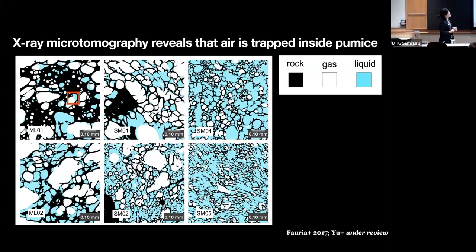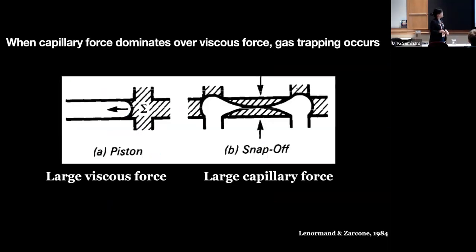Someone did some measurement using a technique called X-ray microtomography. They imaged the distribution of gas, rock and liquid when they did these infiltration experiments. And what they found is there are tons of air bubbles inside the ones that stay floated, okay? And why is that happening? Apparently this is dictated by 2 forces again: the viscous force and the capillary force.